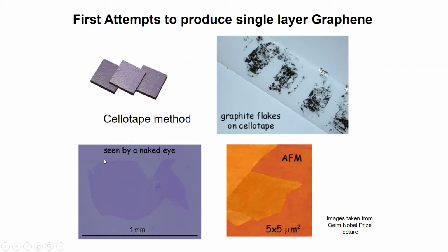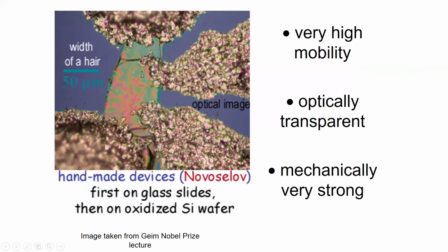So this is actually a single layer of graphite, which is called graphene. And that's the atomic force microscope image of it. And you can image the height difference here, and that correlates with just a single layer of graphene. And then what people were doing is this also has very interesting electrical properties. So again, this was quite crude in the very early days of when they were doing this. This is them trying to put these crocodile contacts on in order to connect up that graphene that they produced and pass electrical currents through it, in order to show the really unique electrical properties of this material. So this was, as I said, a real feat of hard work to produce the graphene in the first place, then connect it up, and then start to show some of these unique properties.